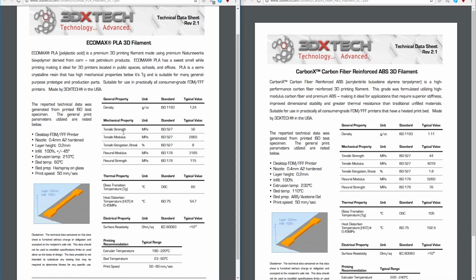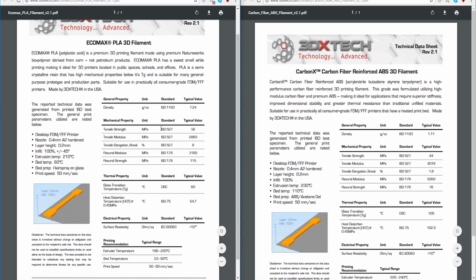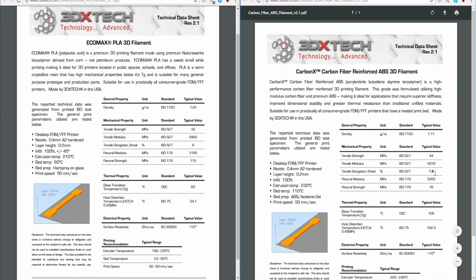So tensile stress, PLA, standard PLA, 56 compared to 44. We'll look at the ABS here in a second. Wow, double the stiffness. We'll compare that to the carbon fiber, but that is really high. But you see the loss in flex here. So the loss in ultimate strain. We went from 10 to 2 to less than 2, right? So drastic loss there. We doubled our modulus, increased our tensile, and then a little bit under, still not nearly as good.